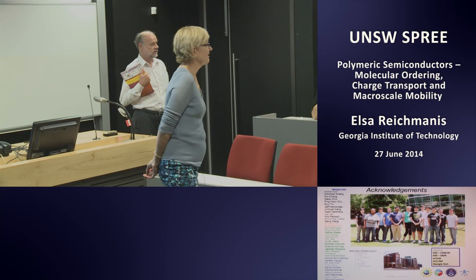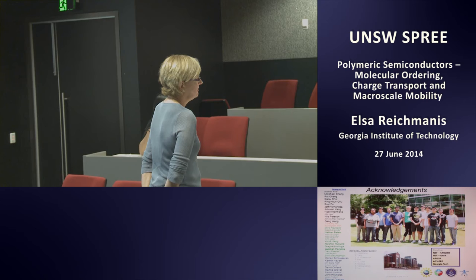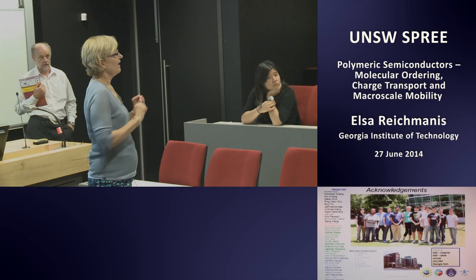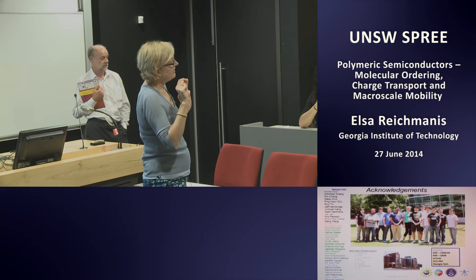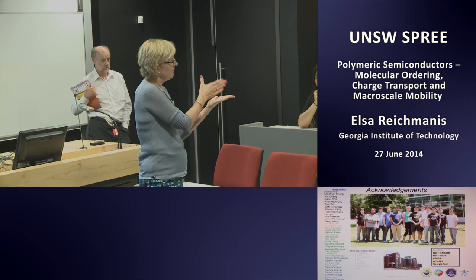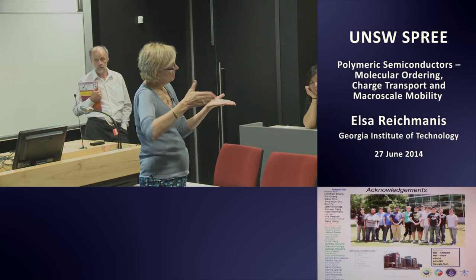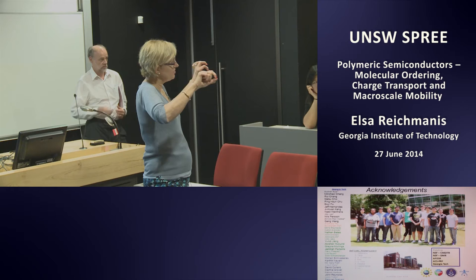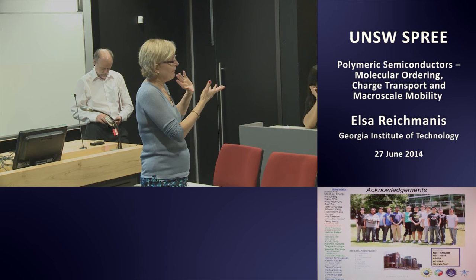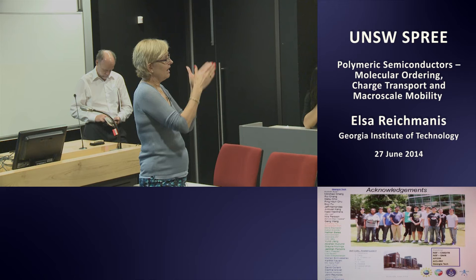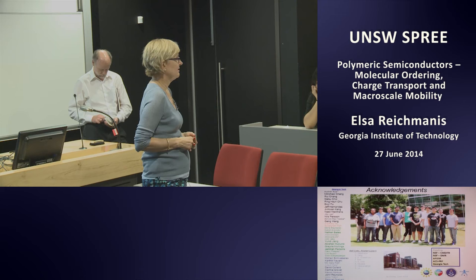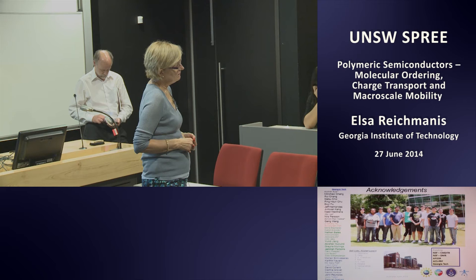We can continue. Okay, is it possible to control the P3HT aggregation, control the size of the fibers? So I believe we can control the size, and I'm not sure how precisely yet, but through the combination of adding a non-solvent and ultrasonication, we can modulate the length of the individual P3HT fibers anywhere from about 75 to 100 nanometers in length up to about 500 to 600 nanometers in length. Also, when the crystal is forming, the orientation can be perpendicular to the substrate surface as well as parallel to the surface.